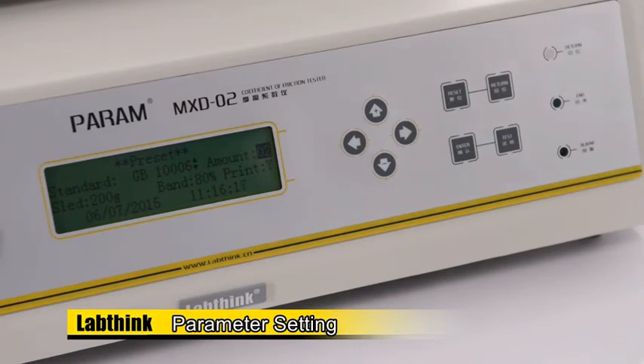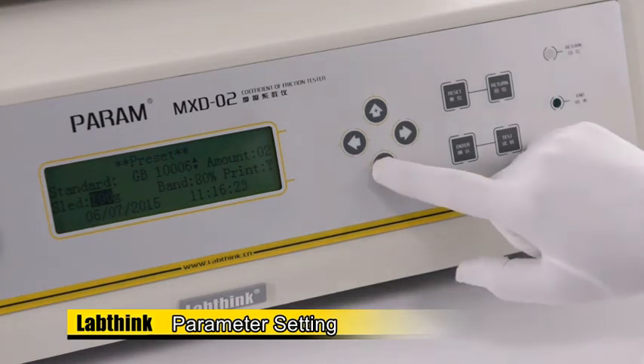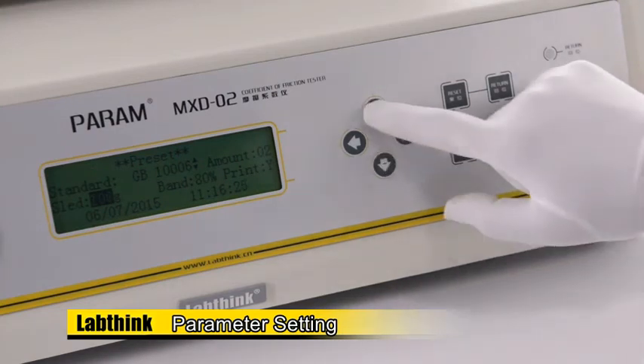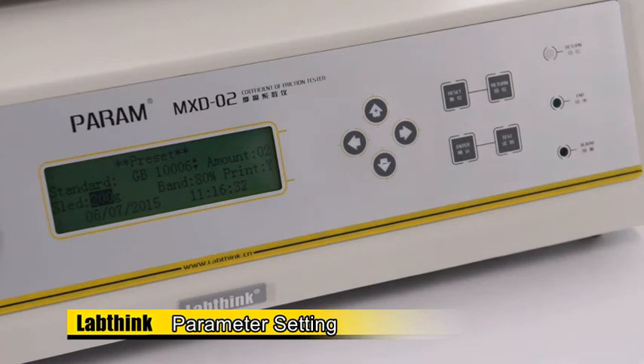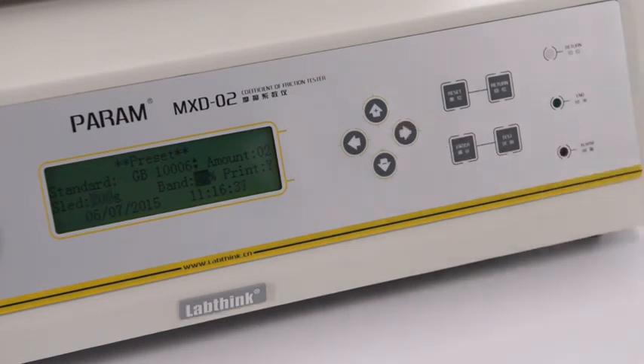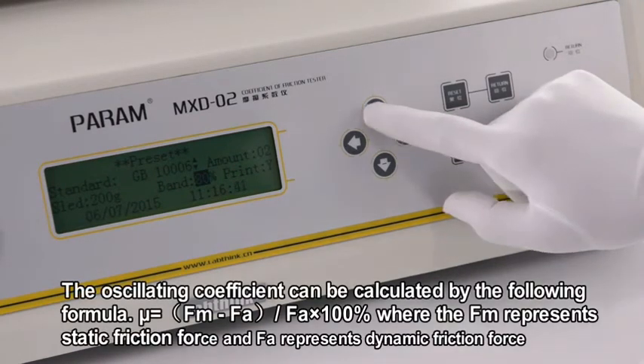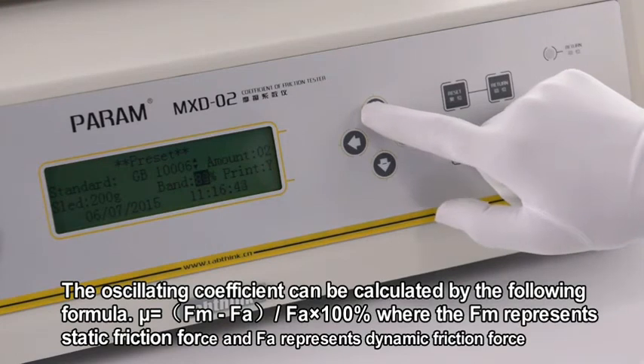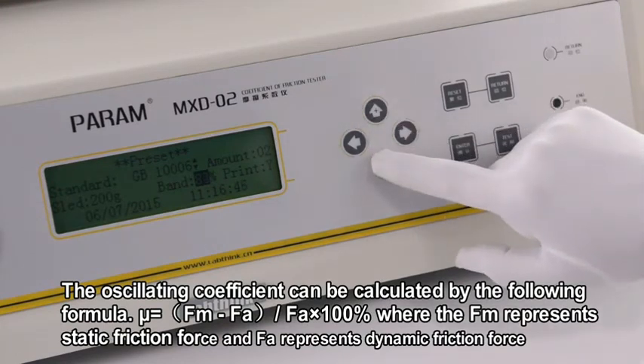Set sled as 200 gram and press Enter to save the setting. Set band as 80% and press Enter to save the setting. The oscillating coefficient band is recommended to be 80%. If it is too low, the system may prompt that the test is failed.